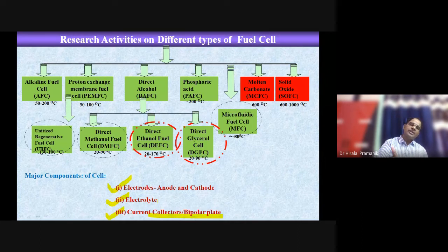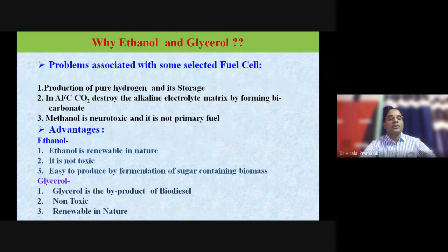There are many other companies, Gore Chemicals, Asahi Chemicals, but their conductivity is not as high as we can have from the Nafion. So Nafion gives the highest conductivity, in the range of 0.1 Siemens per centimeter. Okay, so Nafion is considered the best membrane electrolyte, solid electrolyte, for the fuel cell.